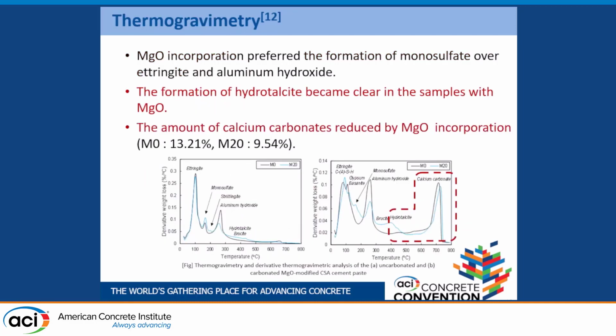These are TG and XRD results of uncarbonated and carbonated samples. As you can see, the formation of hydrotalcite became clear in the samples with magnesium oxide after carbonation. And we calculated the amount of calcium carbonate, and this was reduced by magnesium oxide incorporation. We calculated it by integrating the derivative rate of each, and we found this number.